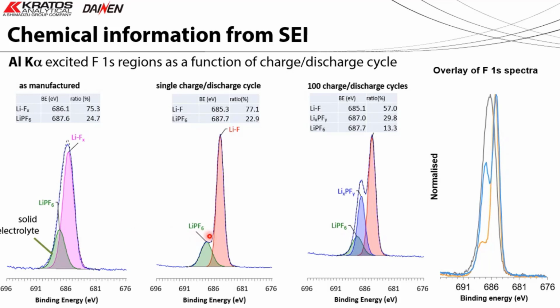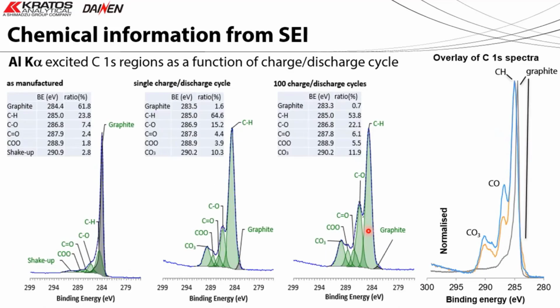After the first charge-discharge cycle, there's a peak which we assign to lithium fluoride, and again we're still seeing some of the electrolyte on the surface of the anode material. And as we go to the heavily cycled sample, we're seeing even more degradation product. So the electrolyte is degrading and forming this layer on top of the graphitic anode. If we look at the carbon region, again, we see a strong component from the graphitic carbon.